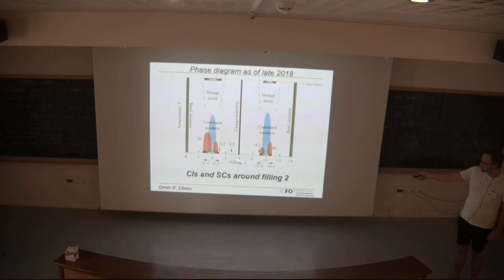We start at charge neutrality, so this is the normal state of the graphene, and we typically have a resistance peak here, which just arises from the Dirac cone which I was talking about. The carrier density goes to 0, so we have a resistance peak. And then if we go either left or right, if we electron dope to +1 electron per unit cell, +2, +3, +4, at +4 electrons per unit cell, because the bands are four-fold degenerate, we end up at full filling, and we get an insulating gap. We have fully filled the Moiré band, we cannot fill any more electrons into the system, and we get an insulating gap. And then of course, if we go to the left side, if we fill -4 holes into the system, you also get an insulating gap. And this is all expected from single particle pictures.